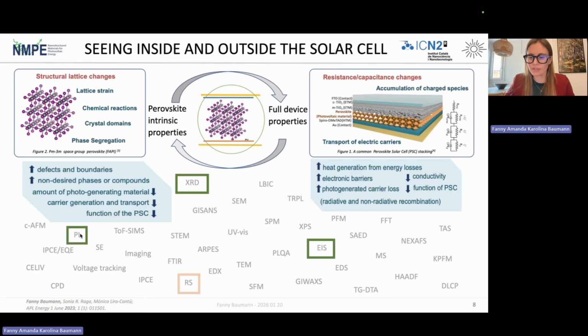Photoluminescence allows us to study the interaction with the material and with light, more specifically the photoluminescence of the film inside the device. X-ray diffraction lets us see the structural evolution inside the perovskites, and impedance spectroscopy lets us see resistive and capacitive changes in devices.